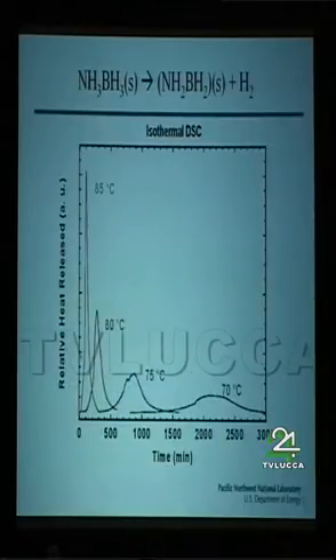And so you go back to the isothermal DSC experiments or with the mass spec, and what you see is you can take this solid, and we're just going to heat it up to various temperatures, 70 degrees, 75, 80, 85. It's an activated process. At higher temperature, the stuff comes off faster. So can we do some sort of simple treatment on this to get an activation barrier for this material?